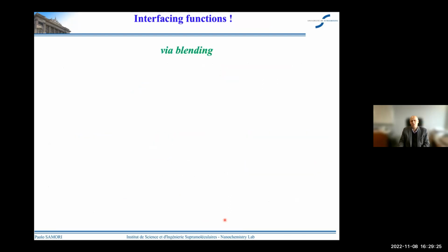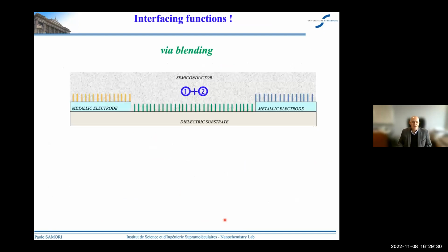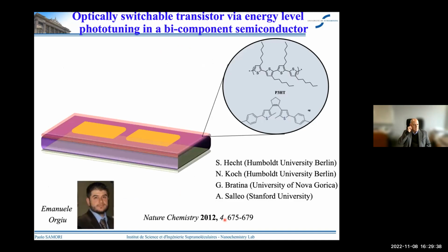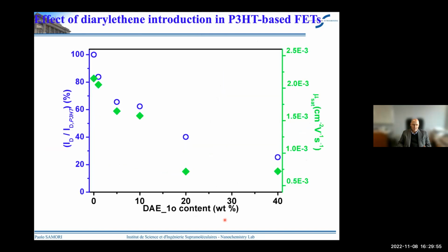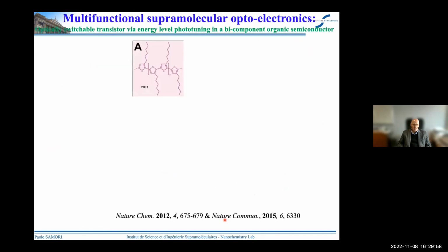Now, another way to interface function is blending. Blending can be done by combining a semiconductor with a photoswitchable molecule. That was done by Emanuele Orgiu, and we decided to play with the most prototypical type of semiconductor, that is P3HT, so polythiophene, combined with diarylethene. Let me show you how this was done.